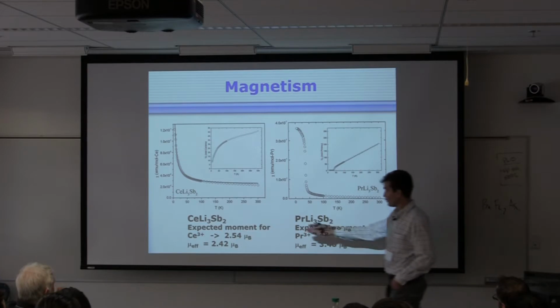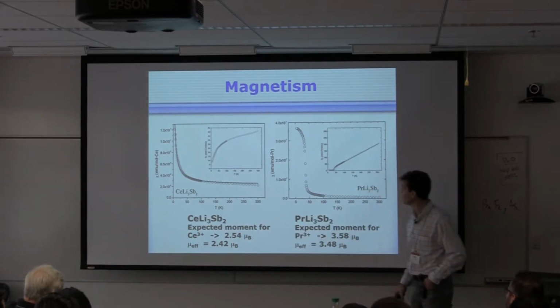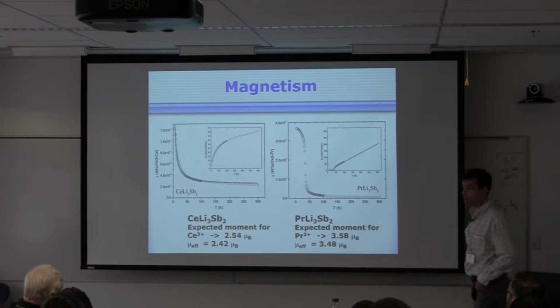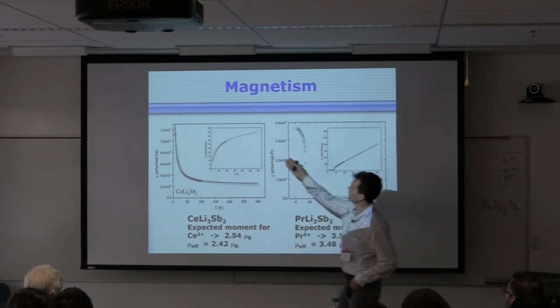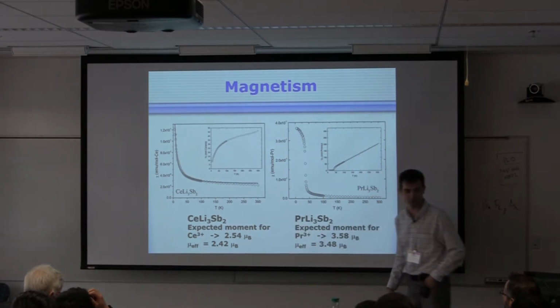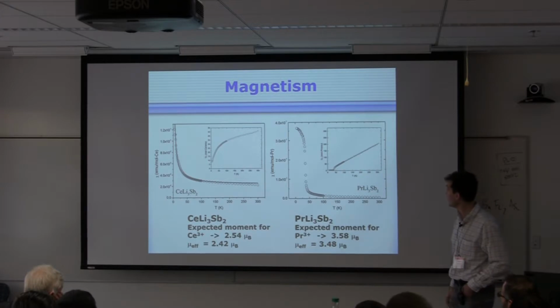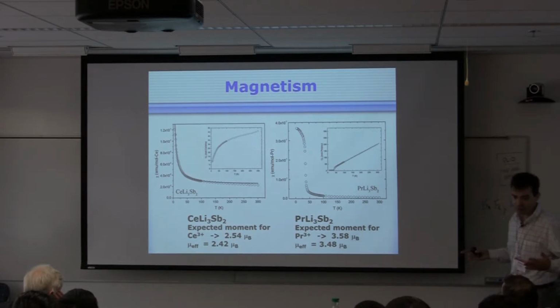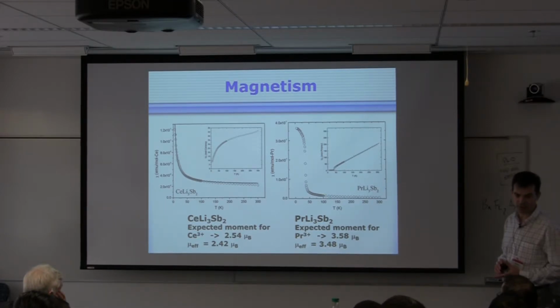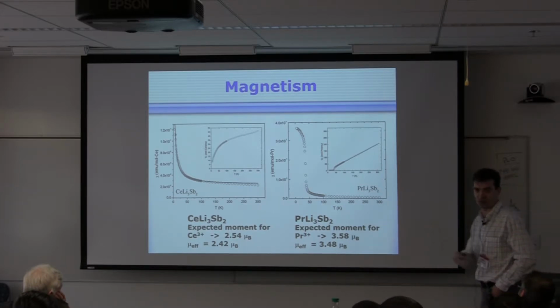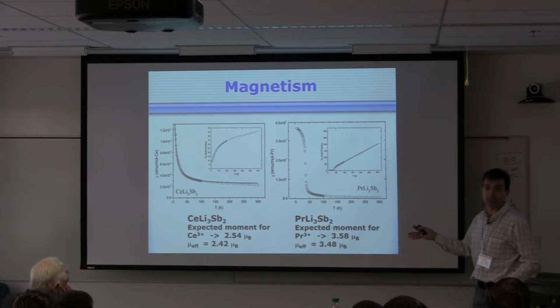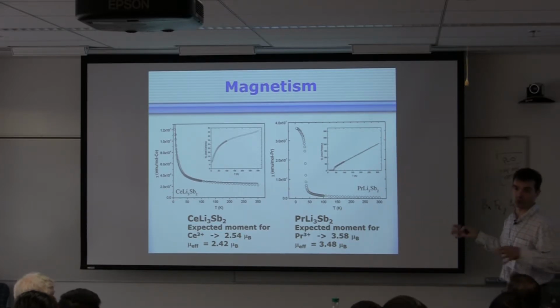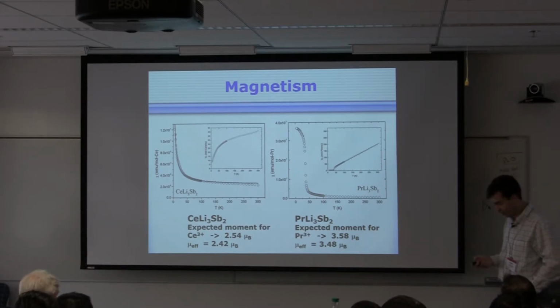This is an isoelectronic substitution of cerium-3 for praseodymium-3. That is just Curie-Weiss behavior, which we can... cerium is never simple to fit into an inverted Curie-Weiss law. But in this case, it's either we have some impurity or something else is happening. No, we don't know. Those compounds are very air sensitive to measure, even in a SQUID, so now we have to put them in quartz. And whether we're subtracting the background, or whether there's some small impurity, I don't know. But that's not the final word on the 1-2s, or what we now call the revised version of the 1-3-2.